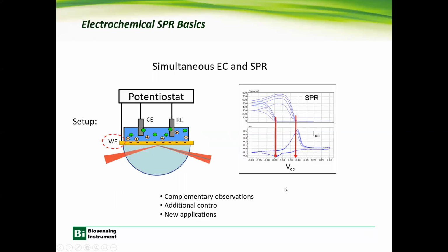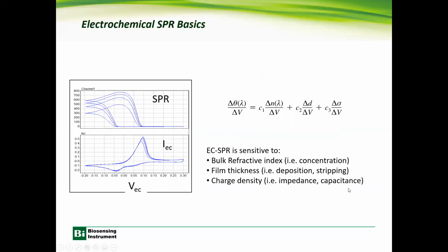So you can see that for the electrochemistry, you measure the CV, the cyclic voltammetry of the process, where the peak shows the electron transfer, the reduction and oxidation of the materials at the surface. And the SPR records the physical property of the interface related to its dielectric constant change, either due to the oxidation state or changes in the film thickness and those parameters. So we'll get more details on that later on.